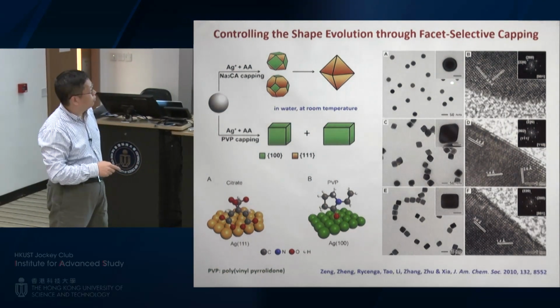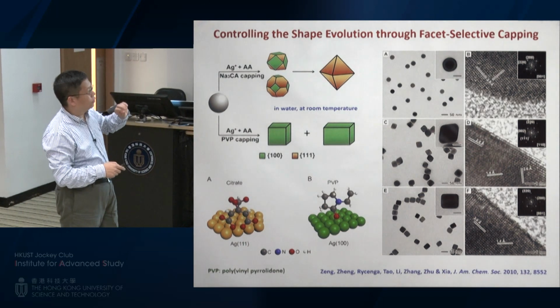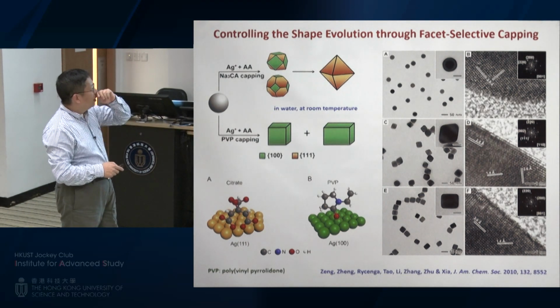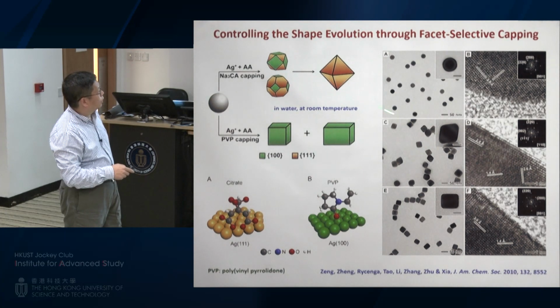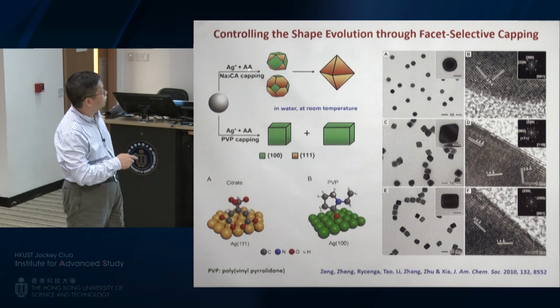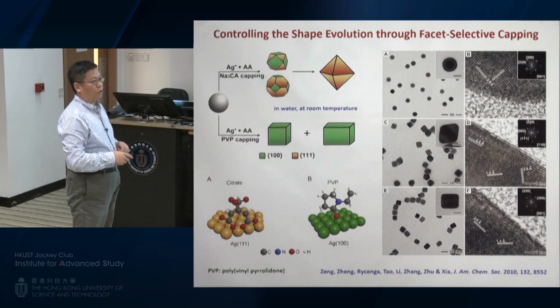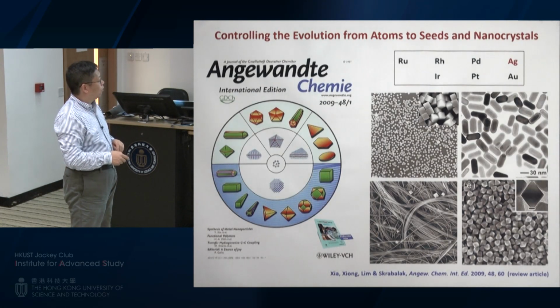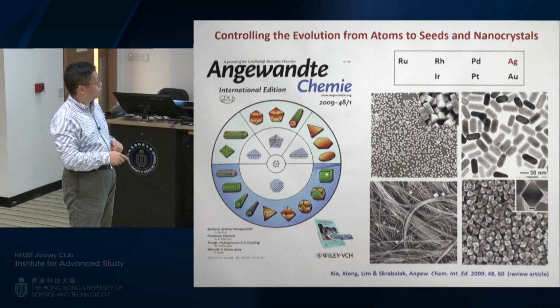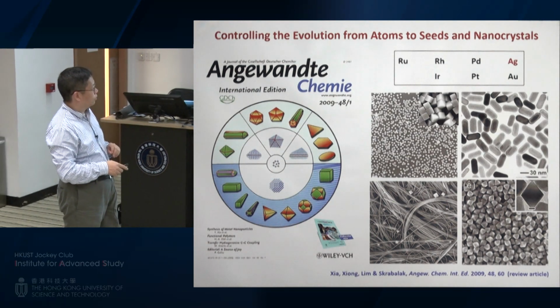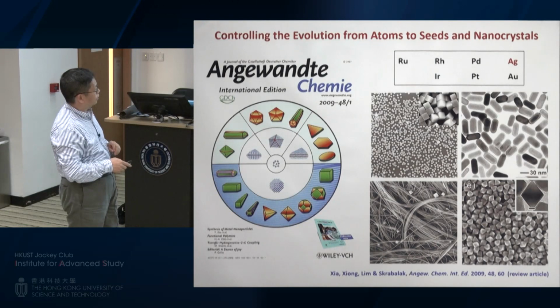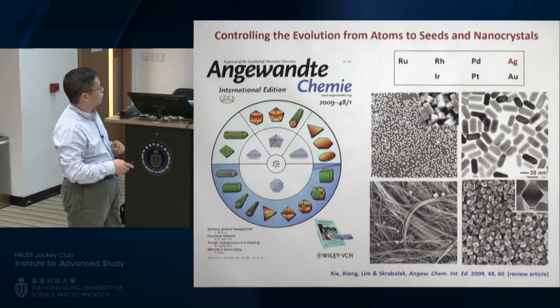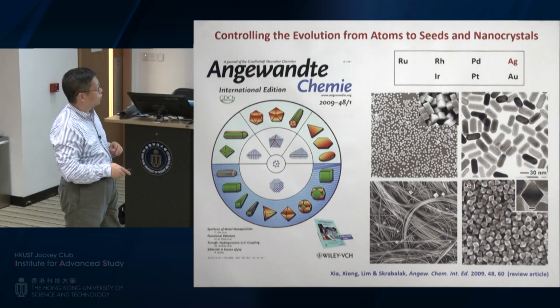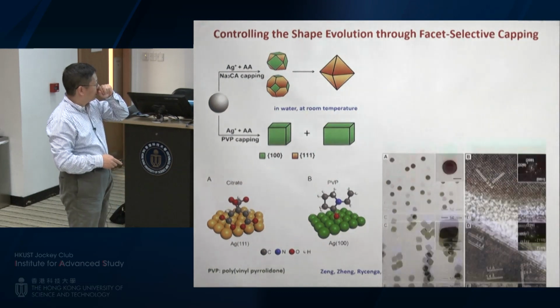So you can see this is a single crystal seed. You have to make sure they are single crystal by doing diffraction or maybe high-res TEM. And then you are going to make octahedra under this capping agent, or you can make a cubic shape if it's under PVP. So you can really see the correspondence. So you can really have almost 100% control. You can make this shape with almost 100% purity in this case. So yeah, we have developed, of course, the capping agent or conditions for all these different shapes. If you're interested, you can look at the review articles shown over here.